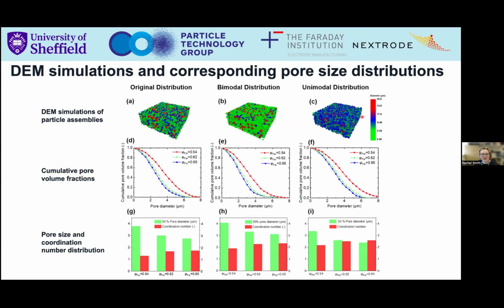So I'm going to go through this reasonably quickly because of time, but we tried to vary many different parameters. We varied the distribution of the particles. So here on the left, we have our original distribution, and this is basically a replicate of the particle size distribution of experimental particles that we had.